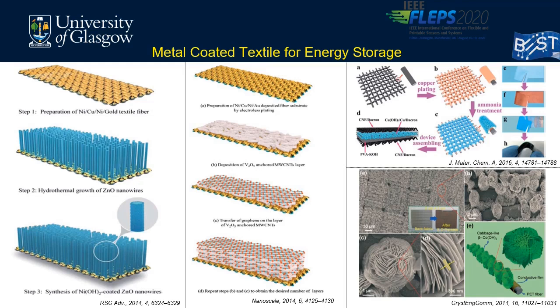So these are some of the reported supercapacitors based on metal coated fabric. Here we can see different types of metal coated fabric. For example, in the first case, the nickel copper and nickel gold, and in the second case also the nickel copper nickel gold are used on the electrode as well as the current collecting material, whereas in the third and fourth case they use the copper as well as the nickel coated fabric for the supercapacitor application.